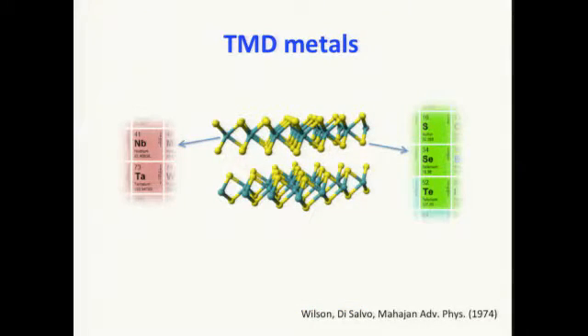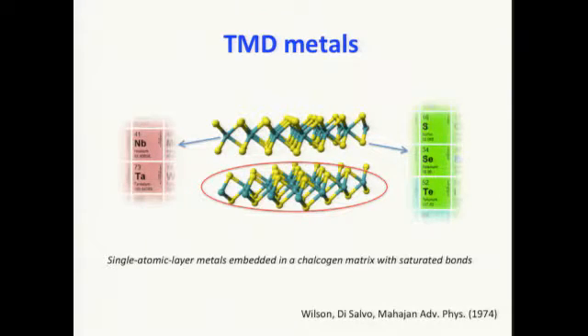The family of TMD metals has a very similar structure compared to the semiconductor TMDs. It's a layered structure, within which each layer has three layers of atoms, with the middle layer of transition metal atoms sandwiched between two layers of chalcogen atoms. And the chalcogen comes from this group: sulfur, selenium, or tellurium. And for the TMD metals, in this case, the transition metal comes from group 5 of the periodic table, mostly niobium or tantalum. So if we can exfoliate a single layer of this material, we can think of it as a single layer of metallic niobium atoms embedded in a chalcogen matrix, so with saturated bonds. So it looks more chemically stable compared to evaporated films.